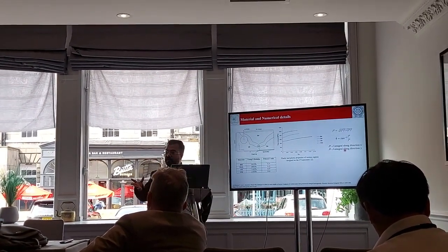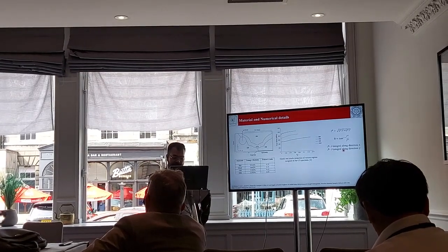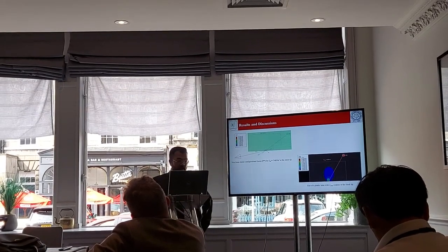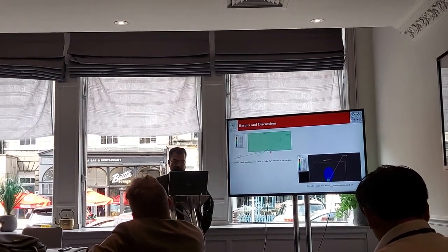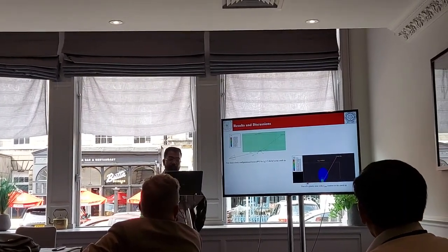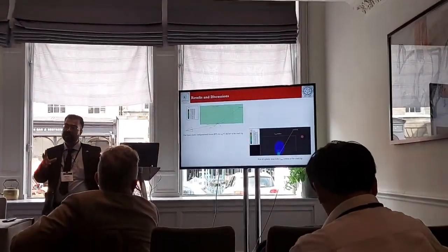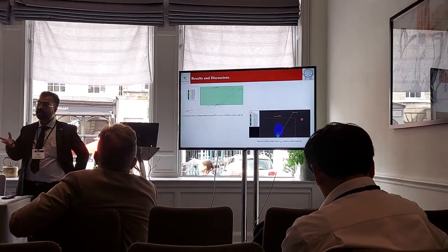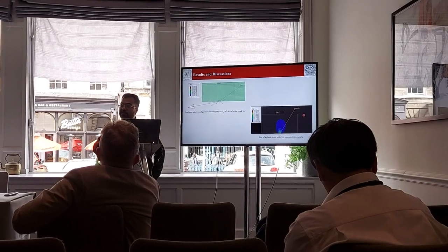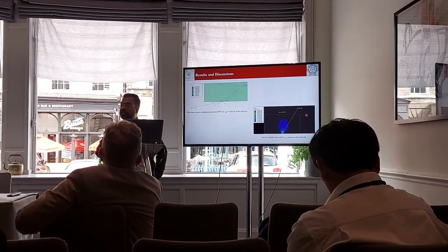And this scenario is complicated because we have a lot of deforming material which are deforming differently in the same case. So this is just a picture of the configurational forces which we run in finite element analysis using post-processing, and this is the plastic zone. It can be a creep zone also. So if you take a contour which is outside the deforming zone, then the elastic plastic J integral and conventional J integrals are the same. So this idea can be used in creep also. We have used it. Again, day 3, you should watch that presentation.